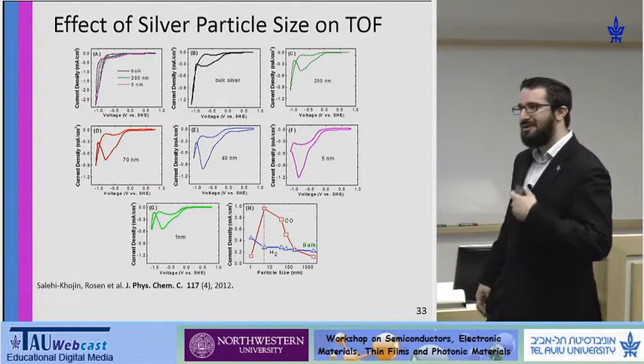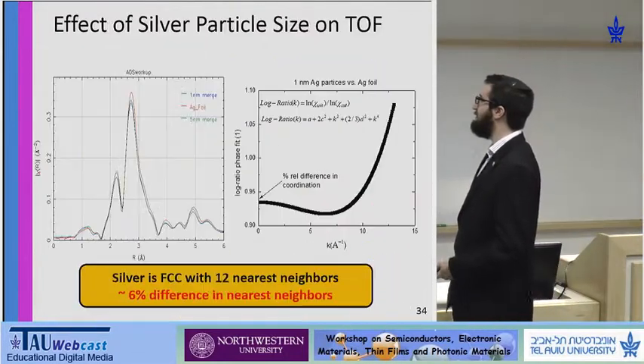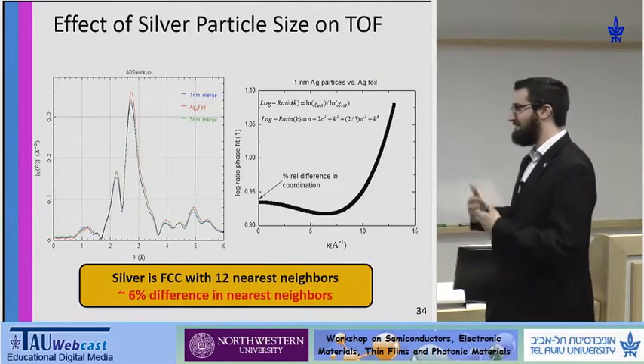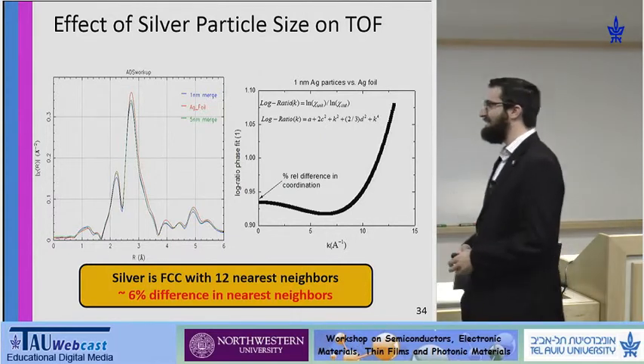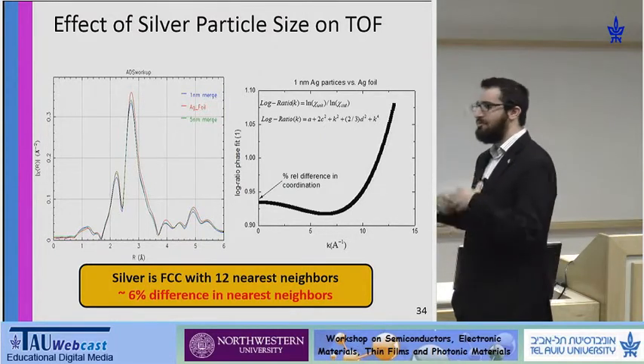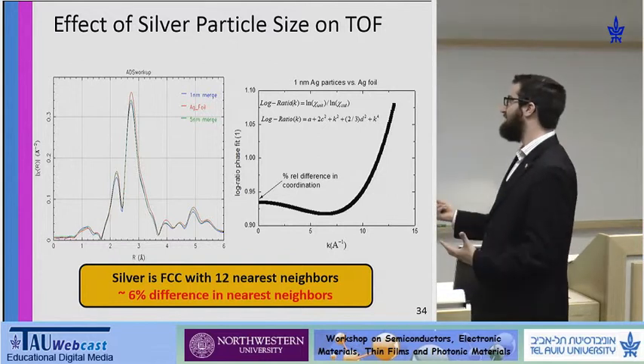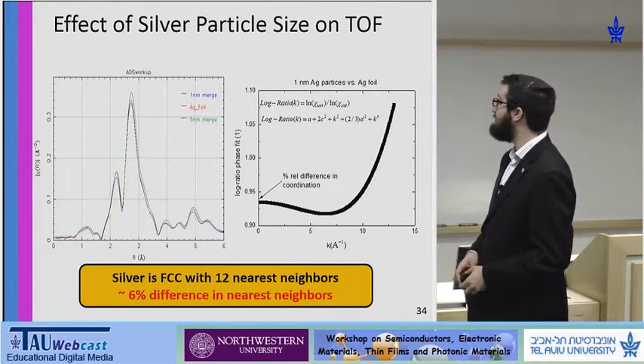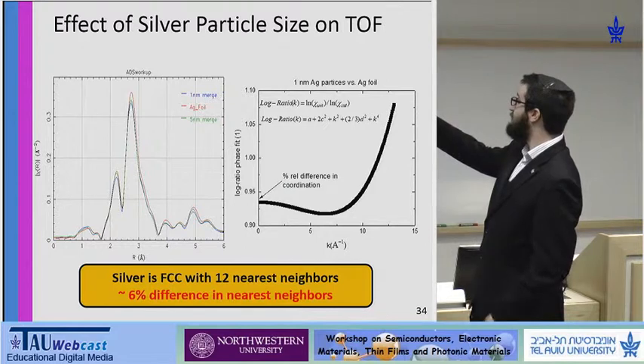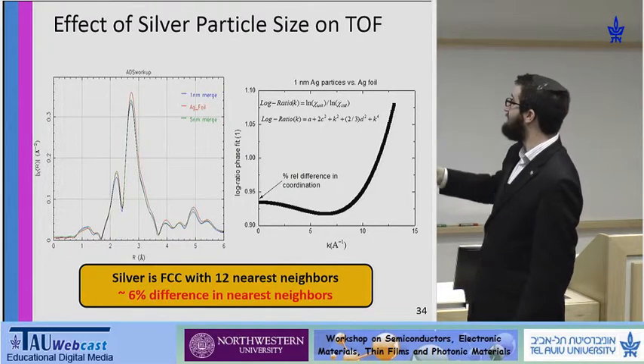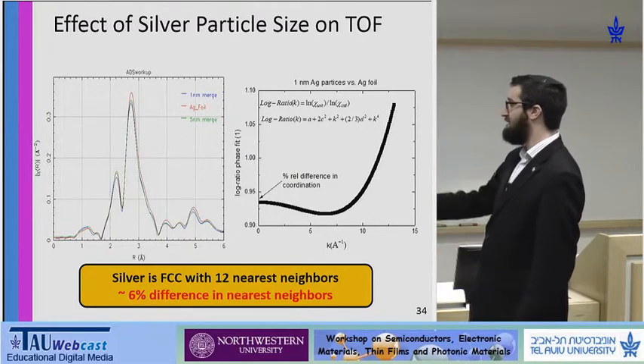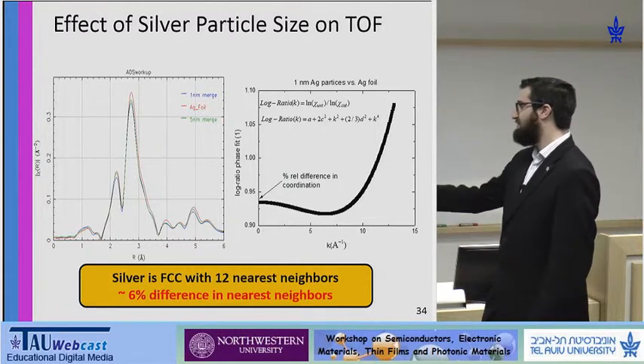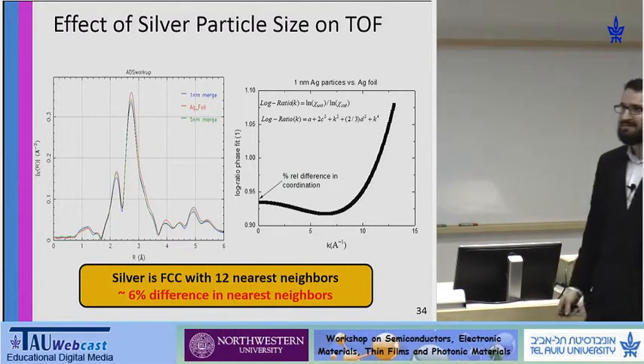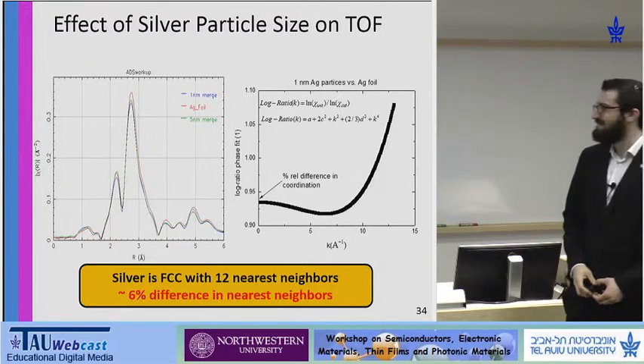So looking for an explanation of this behavior, the first thing we looked for is, is there a significant change in nearest neighbors? Are we making low coordinated sites? And the answer, based on synchrotron analysis, is that the difference between bulk silver and 1 nanometer silver, as far as the coordination, is about a 6% difference. FCC silver with 12 nearest neighbors, this comes to less than an atom difference.